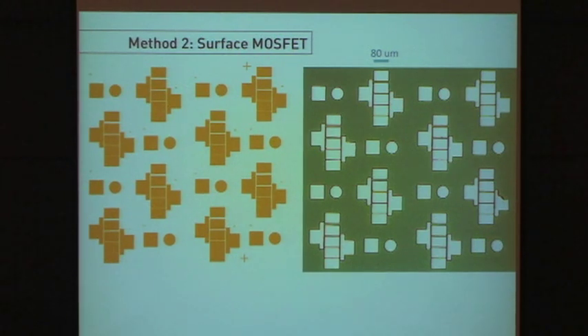This is the most sensitive step in our process because gold lift off is notoriously kind of tricky to get the right spacing, but you can see in the picture that we had these very fine lines in the bottom rectangles. Those are about three micron gaps, meaning that we can at least get that minimum resolution.